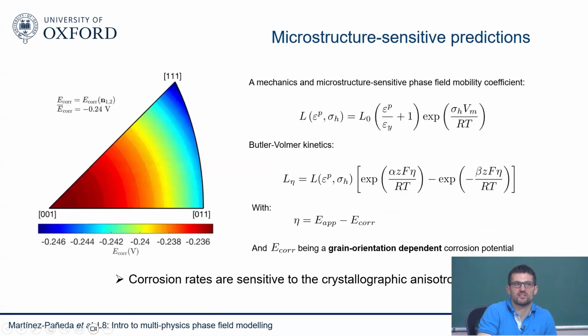The other aspect is the role of the microstructure. So we want to develop microstructure sensitive predictions, and we know that there's two effects of microstructure. One is the crystal properties, the mechanical crystal properties will change in space. There will be an anisotropy dependence related to the grains that you're having. But also, the corrosion rates are shown to be sensitive to the crystallographic anisotropy. So they vary something along what you see here. So the idea is to incorporate this into the model.